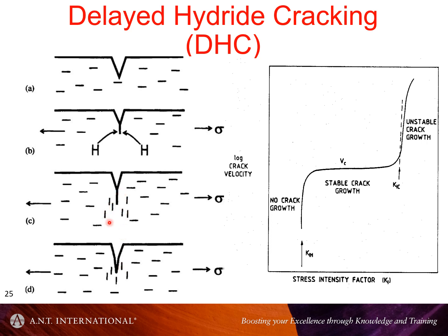The reason it cracks at a certain size is still subject to various theories and hypotheses. But what that means is that once you're in a regime, both of stress and temperature, where you can get this hydrogen accumulation at a crack tip, once we exceed a certain stress intensity, which is related to the stress, we can have this effect happening. We surpass a certain threshold, and we get into a stable crack growth region in terms of the crack velocity.